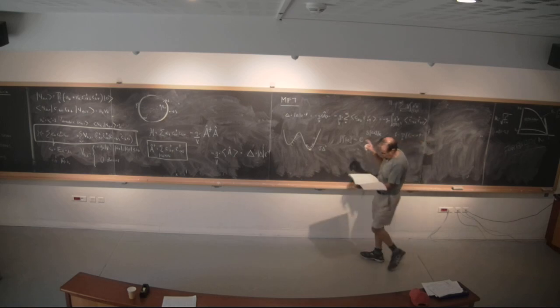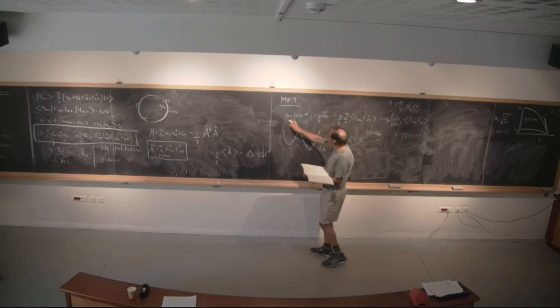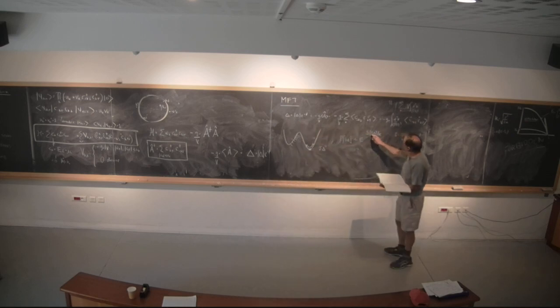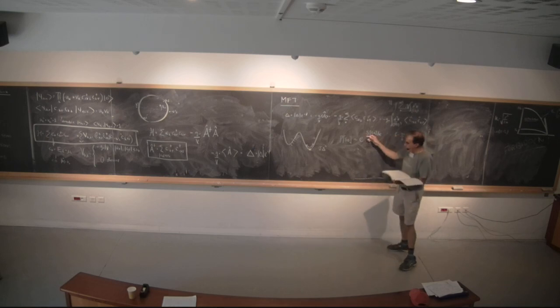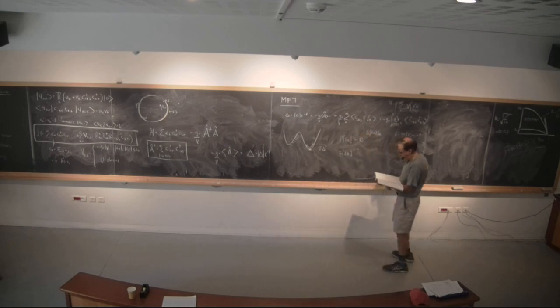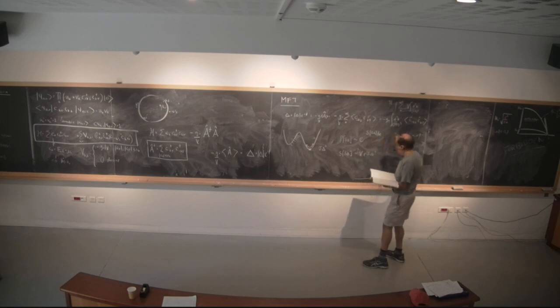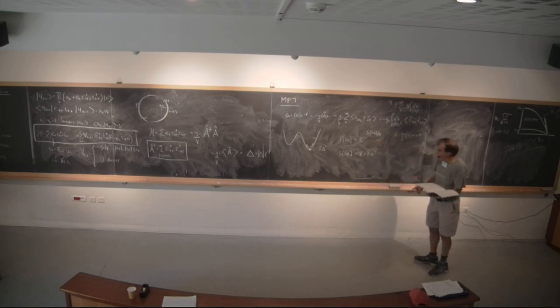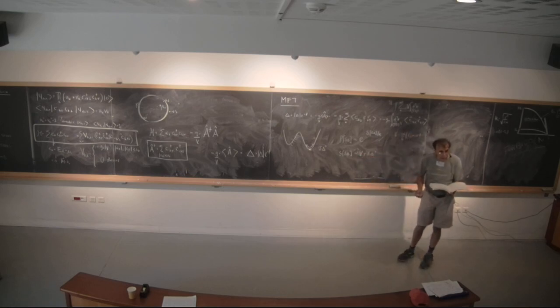The only important part about this argument is that the action associated with a fluctuation in delta, which is for the whole system, is of order the volume. So this S of delta lambda, if we think about it in Landau-Ginzburg theory, will go like the volume times R times delta lambda squared. The important thing here is it goes like the volume. It's extensive, okay?